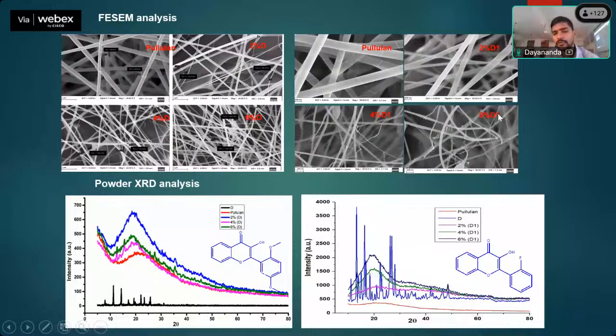This is dopant one, where the fluoro derivative of 3-hydroxyflavone was used. But the morphology was completely different - the fiber was not continuous, it was cut in between. So that is how once you add the dopant, the nanofiber mat will be varied completely, it will be changed.